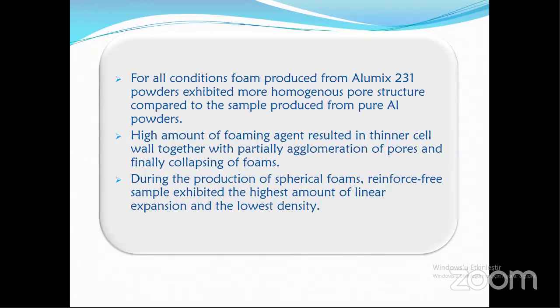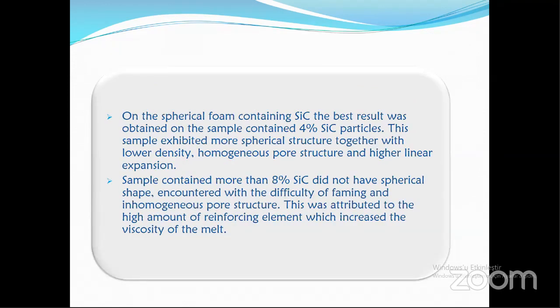For all conditions, foam produced from Alumix 231 powder exhibited a more homogeneous pore structure compared to samples produced from pure aluminum powders. A high amount of foaming agent results in a thinner cell wall, together with partial agglomeration of pores and finally collapsing of foams. During the production of spherical foams, the reinforcement-free sample exhibited the highest amount of linear expansion and lowest density. On the spherical foam containing silicon carbide, the best result was obtained on the sample containing 4% silicon carbide particles. This sample exhibited a more spherical structure, together with lower density, homogeneous pore structure and higher linear expansion.